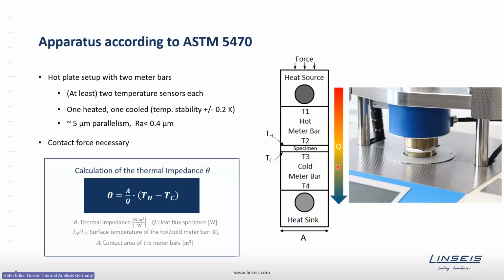The basic setup of the TIM tester is having these plates, or we call them meter bars, where one is heated and the other one is cooled. The upper one is heated and the lower one will be cooled using an external chiller, and in between the sample will be clamped in. Due to this temperature gradient, a heat flow is established. We'll wait until this heat flow is in a steady state, so it is constant.